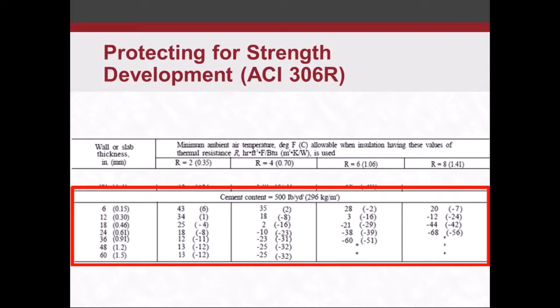I'm going to go to the next slide. It blows this up a little bit more. This is a great table, by the way, especially for contractors. Here we've got the minimum ambient temperature allowable when insulation having these values of thermal resistance is used. So these are the air temperatures right here. Again, this is our section thickness, 6 to 60 inches. And these columns here correspond to different R values: R value 2, R value 4, and R value 6. And these are the air temperatures that it can get down to and still maintain a 50-degree temperature.